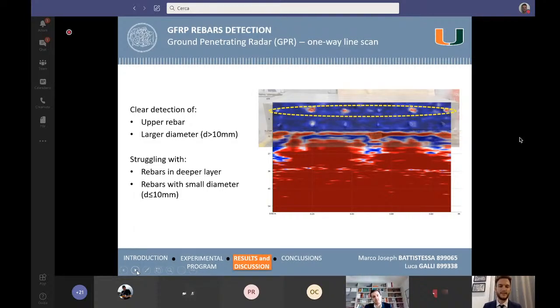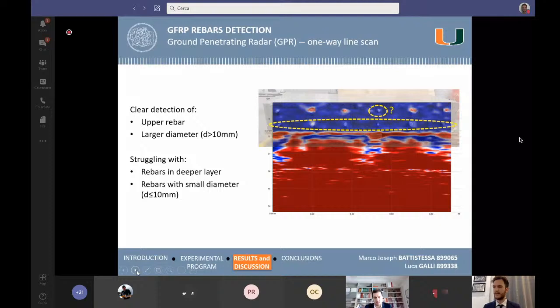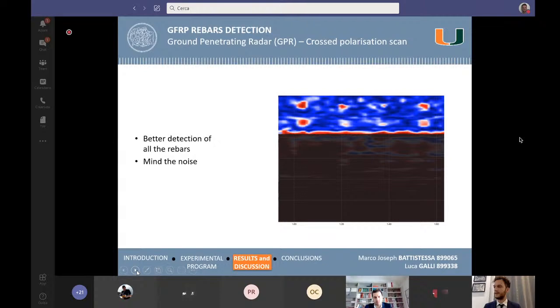Here we can see better the results from the one-way line scan, and as you can see, the rebars in the upper layer have been more clearly detected, as is clear if we overlap the picture of the slab, except for the smallest one, which is rebar number 3, whose nominal diameter is 10 millimeters, which is not detected, as well as the rebars in the bottom layer, except for rebar number 5, whose nominal diameter is 16 millimeters. Then we performed a cross-polarization scan.